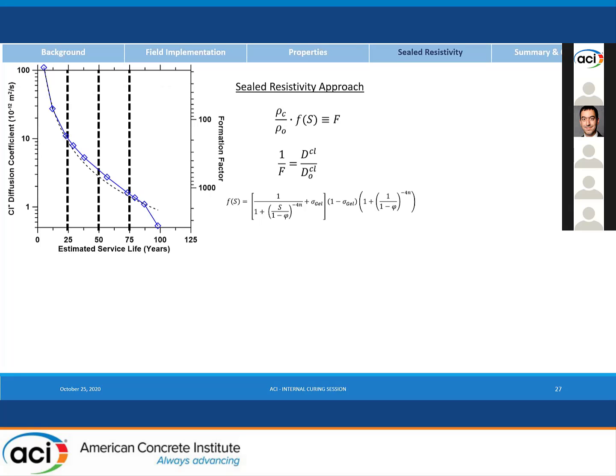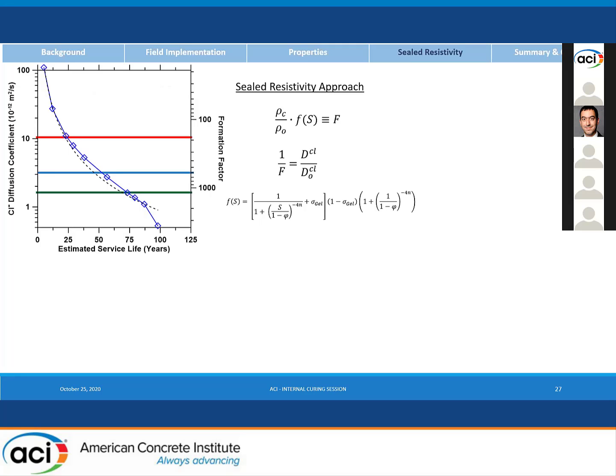But what I would say is that what we can do with this type of approach is we can now begin to look at, well, what service life do we want to specify? So we can say 25, 50, 75 years, and then we can come up with either a specifiable chloride diffusion coefficient, or in my mind equivalently, the formation factor, which is being pushed heavily. So we can rearrange these things and come up with a target design resistivity based on the design diffusion coefficient or formation factor. We can correct to the measured value that we expect using the saturation function. We just need to agree on what that is. And then we can apply some statistics to it.